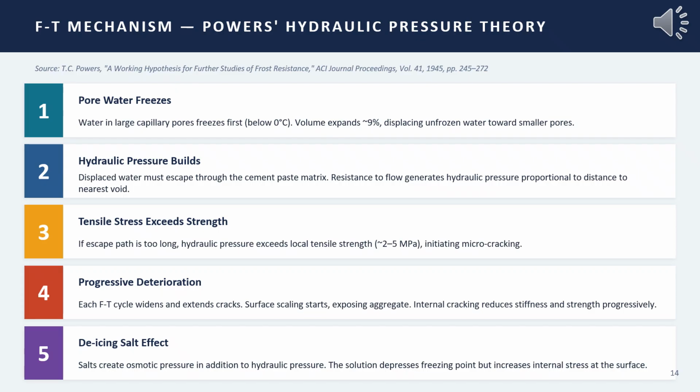Step 2. This displaced water must find somewhere to go. As it moves through the narrow capillary channel, it encounters resistance. That resistance generates hydraulic pressure. And T.C. Powers showed that this pressure is proportional to the distance the water must travel to reach an escape point.